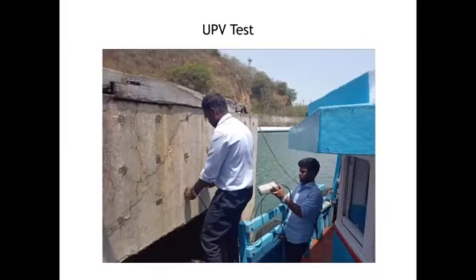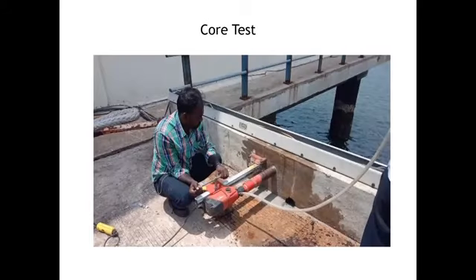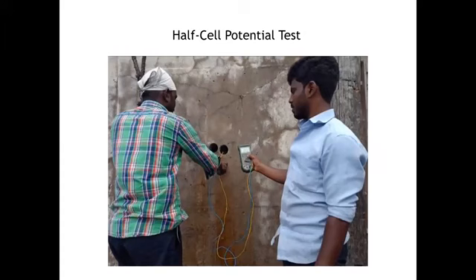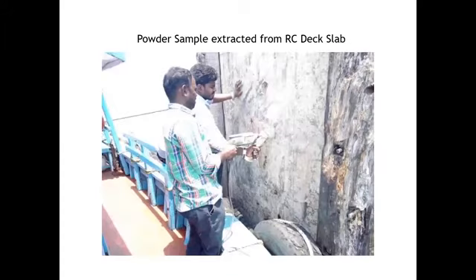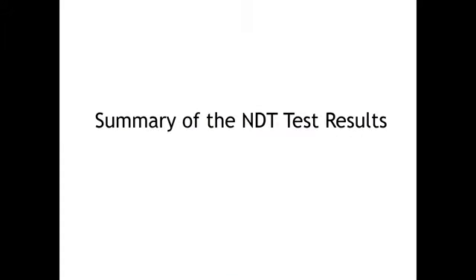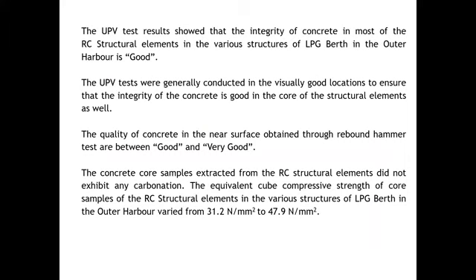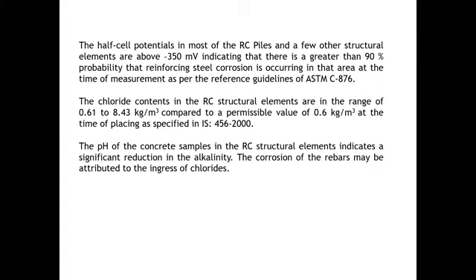What we do is the rebound hammer test, ultrasonic pulse velocity, extract the core, and then do half-cell potential, which is very, very important as far as marine structures are concerned. Then we collect powder samples, test them at the lab, and come to a conclusion about what you are going to design. Now UPV is good, and the quality of concrete near the surface is good to very good with the rebound hammer, and from the cores you get values of 31 to 47 or 48 MPa. But if you look at your half-cell potential readings, which are almost minus 350 everywhere, and your chloride content, from 0.61 kg to 8.43 kg as maximum, you are going to have corrosion.